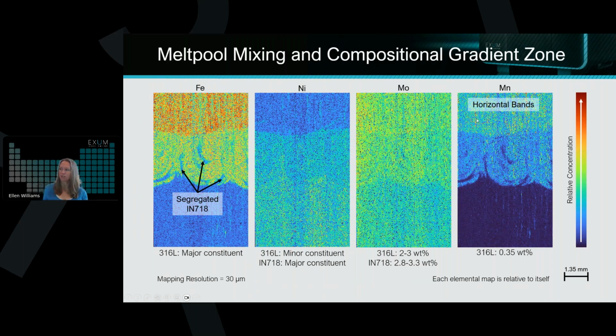The other thing that the researchers noticed from these results were these horizontal bands that you can see occurring once we've transitioned. You can even see it on the nickel alloy side as well, that they interpret as being some dendritic features that are occurring in this printing process. So again, certainly there's plenty of characterization going on here that can then inform the next iteration of these builds and inform the process improvements to minimize how many defects we may potentially have.